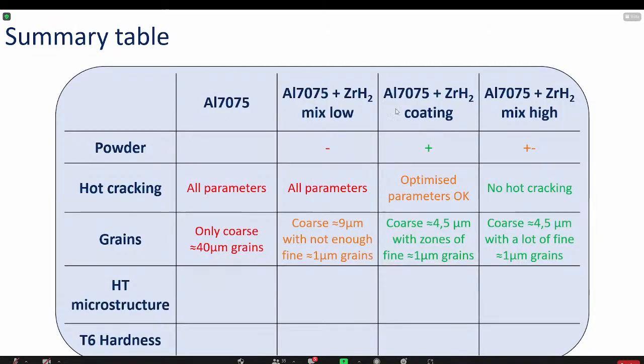And if we go to a small summary table, like I've said, the coated powder is better regarding the zirconium distribution. Then concerning hot cracking, the powder mixed with a high content of zirconium shows no hot cracking whatsoever. The coated powder shows no hot cracking for the optimized parameters, but the two other powders show hot cracking, which we want to avoid. And it is mainly because the coated powder and the high content zirconium powder have really small grains, which avoid the hot cracking.